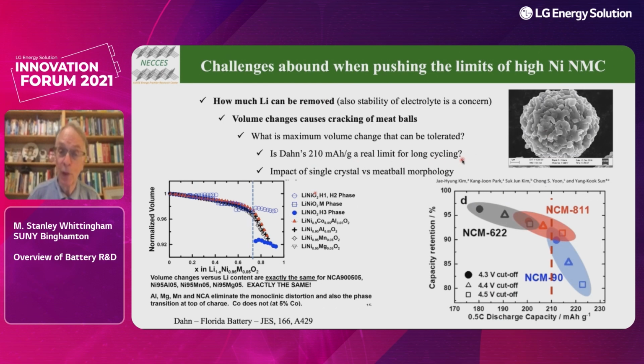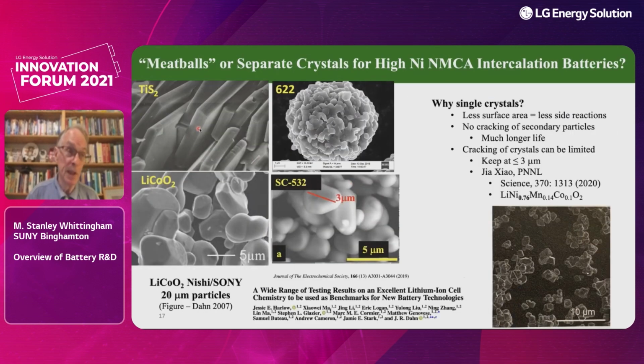And do single crystals really help? I'll just show you a few single crystals. So we go back 40 odd years. Here's TiS2 where we used single crystals. These were huge single crystals, hundreds of microns across. If you go back to Sony's original work, by Nishi and others, they used single crystal particles exceeding 20 microns. This particular picture is one of Jeff's, and his are about 5 microns, but they use large particles for safety reasons. Here is today's meatballs, 622, and here is, I think, Jeff's material with 532 and his single crystals.